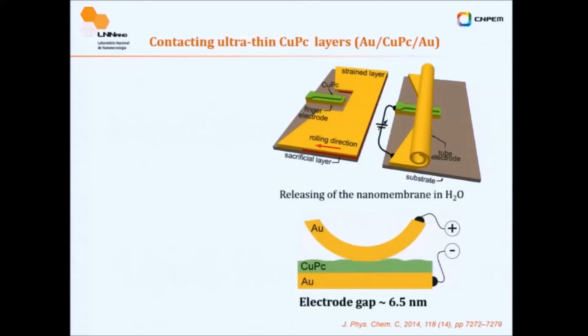Even though we managed to do a lot of investigation down to 6.5 nanometers, with phthalocyanines for instance, here we developed a system with a strained layer and a finger where you put our copper phthalocyanine. When you remove the sacrificial layer, the tube tends to roll and stop on top of your finger. So in the end, what you have is gold, copper phthalocyanine, gold. Quite a standard junction. The difference is we are measuring not 50, but 6.5 or around 6 nanometers.